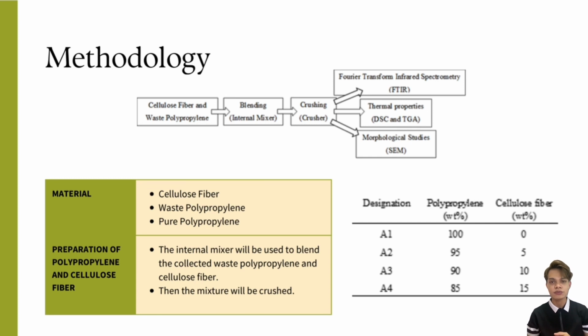The internal mixer will be used to blend the collected waste PP and CF. The table below shows the blend composition percentage by weight of PP and CF that are used. The blending process will be carried out at 180 degrees C temperature, 40 RPM rotation speed, and 5 minutes residence time. The sample will then be crushed for the characterization testing. The schematic diagram of the overall methodology is shown in the figure.